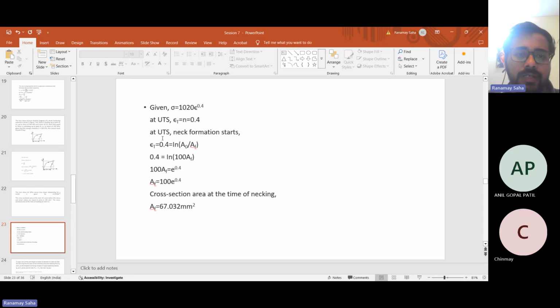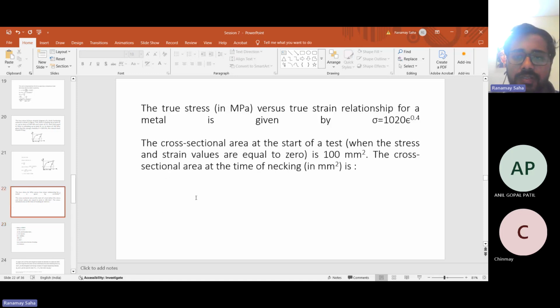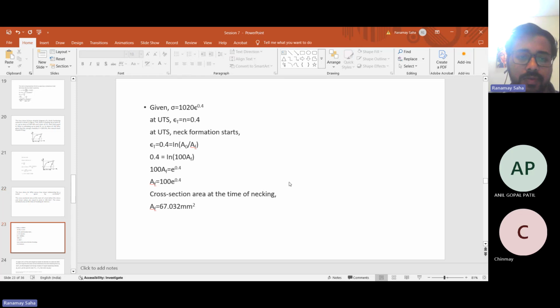So at ultimate tensile strength, neck formation starts. The true strain epsilon_t equals the n value, 0.4, which is ln of initial to final area. From that you can find AF to be 67.032 millimeters squared. So you can see how much it is reducing from 100 to 67, beyond which the material starts to fail.